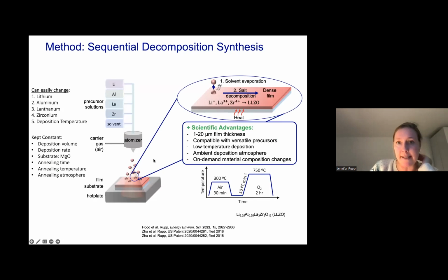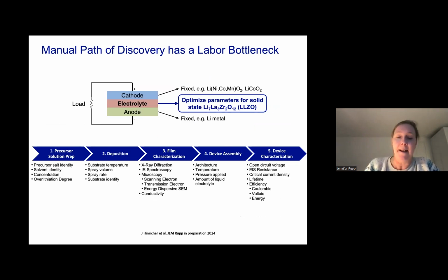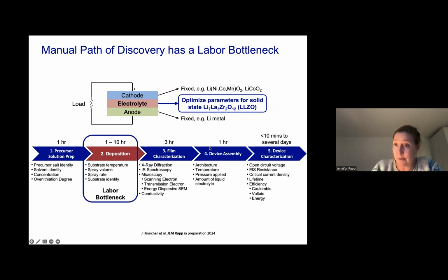So we have created a method called sequential decomposition synthesis. We vary the different cations in it. We vary the solvents. And we want to probe different annealing protocols, which phases we can access, and just create a phase diagram of it on the fly, really for solidified films. And this is a little bit on where my student, Jesse Hinricher, who is really in this project, was analyzing why this is so important.